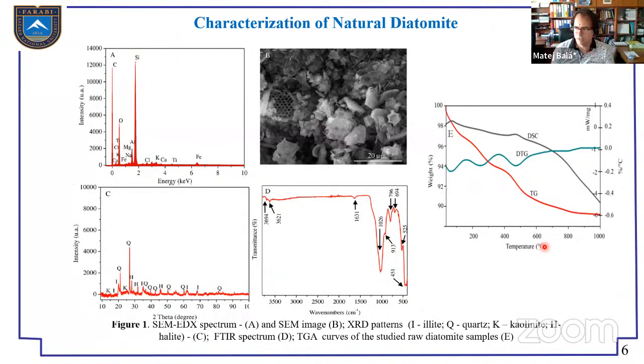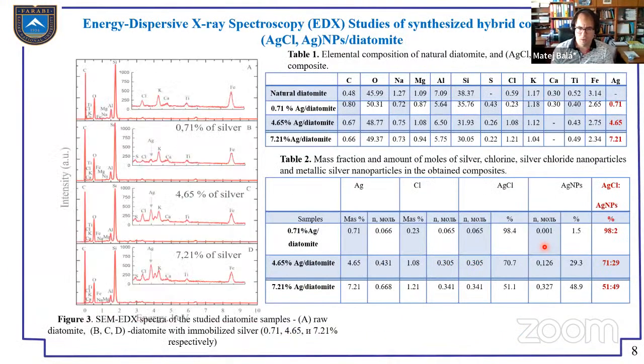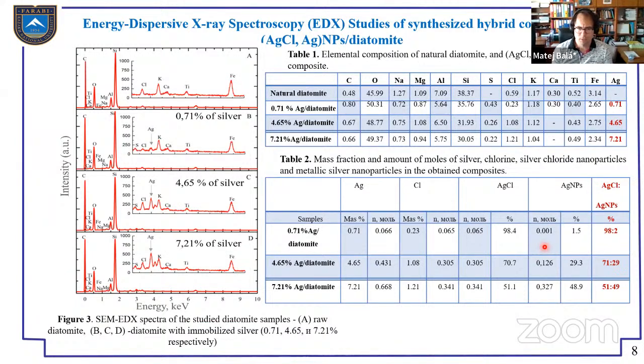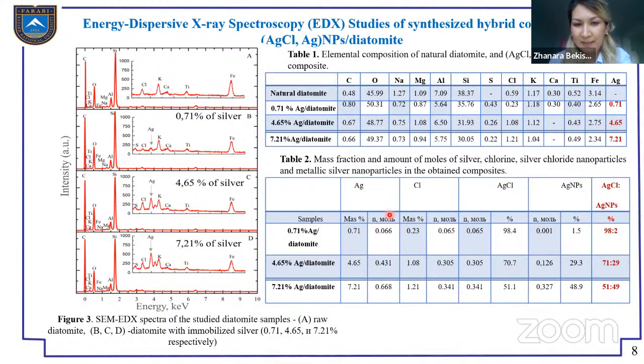Okay. Perfect. Then on slide 8, it's quite a general question. How exactly was the ratio between the silver, I mean elemental silver, and silver chloride determined? Was it based on the EDS results? Yes, we calculated from the same EDX. It was the amount of the silver and the amount of the chlorine ion which reacted with the silver, and this is in molar fraction, moles of the silver and silver chloride. And we can see the mole of the silver and the mole of the chlorine, and the remaining amount is the metallic silver, which doesn't react with this halide, the excess of the silver which was reduced.